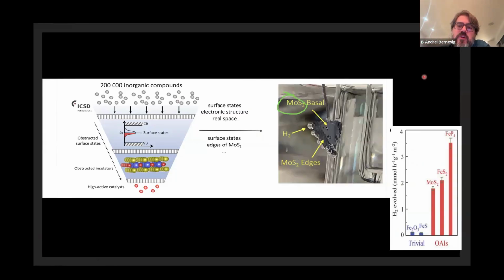But basically what you can see is that its catalytic properties depend on the surface at which you cut the material. So for example, here, there's no catalysis. You don't see any H2 bubbles accumulating. Here, there's no catalysis either on the surfaces. But on the edges, where surfaces touch with each other, you can see heavy catalysis.